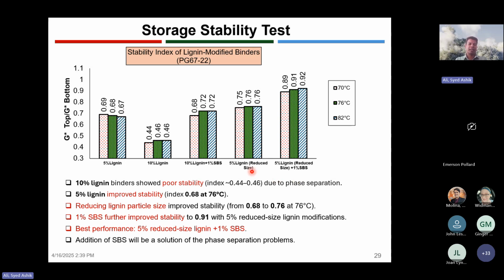So we reduced the particle size, and we added those reduced particle size lignin to the asphalt binder, and we found that it improved the storage stability by quite some degree, around 0.76 from 0.68 to 0.76. But again, we wanted to improve it more and wanted to find out what can be done to improve it.